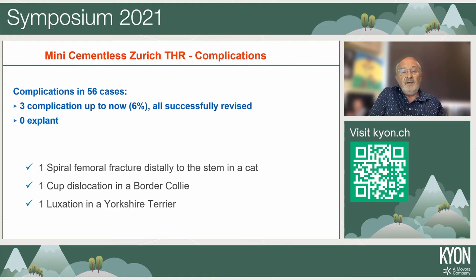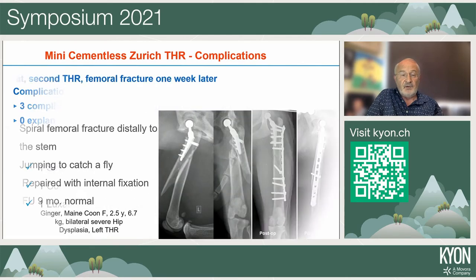About complications, we had 3 complications. At the beginning, for the first 35 cases, we had no complication. I was quite worried, because some complications are required: we can understand very much from the complications how to improve our surgical technique, case selection and implant selection. So we had one spiral fracture of the femur distally to the stem in a cat, the first cat I did, a cup dislocation in a border collie, and a luxation in a Yorkshire Terrier.